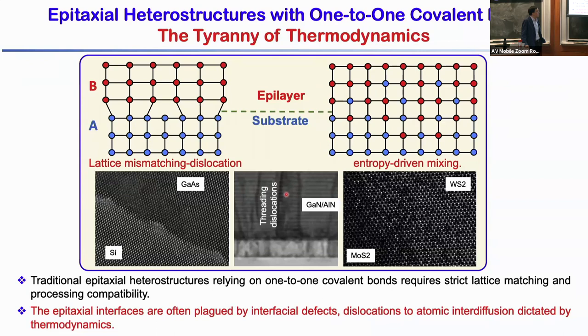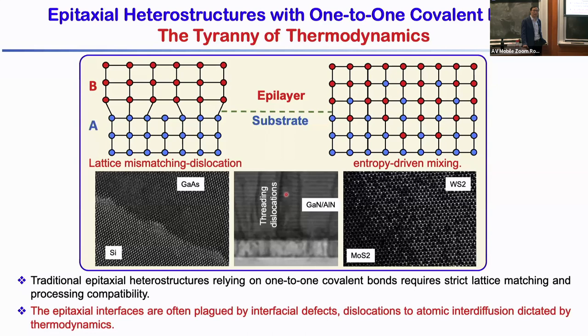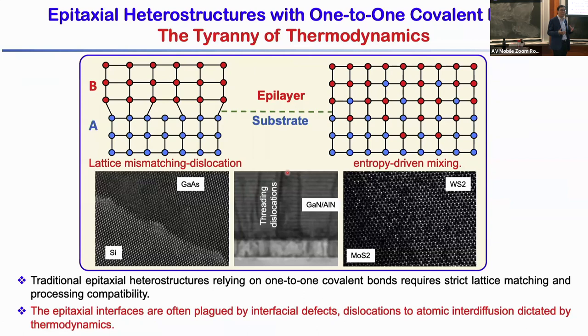Additionally, epitaxial growth usually has to be done at relatively high temperatures. Even if we have perfect lattice matching, at high temperature there's atomic diffusion — interdiffusion — basically forming an alloyed interface without a sharp interface. This can compromise the structure we originally wanted. To optimize any such structure very often takes years of effort and very expensive equipment. For this reason, all these powerful technologies are really limited to a few selected materials — mostly silicon-based transistors or III-V based materials.